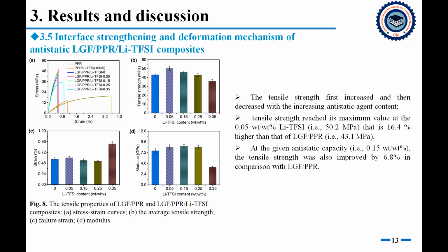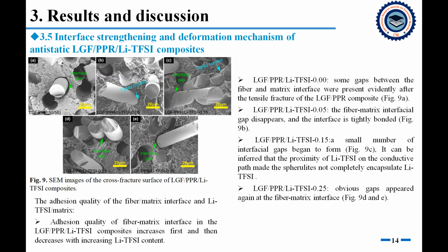Through the tensile mechanical performance test, we obtain the stress-strain curves of different composite materials. The tensile strength first increased and then decreased with the increasing antistatic agent content. Tensile strength reached its maximum value at 0.05 weight%. At the given antistatic capacity, such as 0.15 weight%, the tensile strength was also improved in comparison with the long glass fiber reinforced composite.